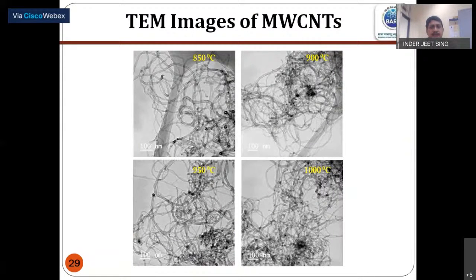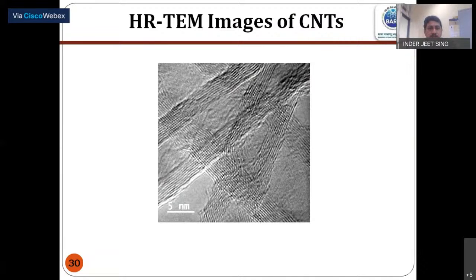And this is the typical TEM images of multi-wall carbon nanotube at different temperatures. You can see how they look. And this is the high resolution TEM, where you can count the number of planes of carbon, which is typically 8 to 13.